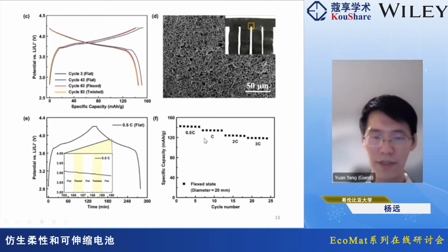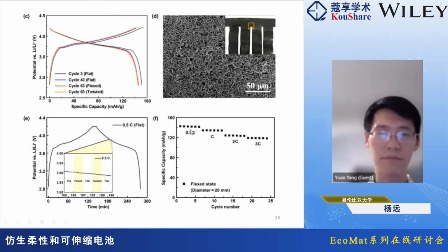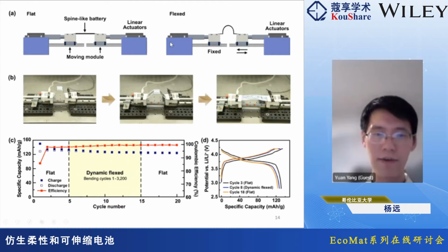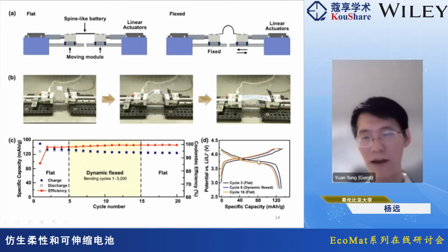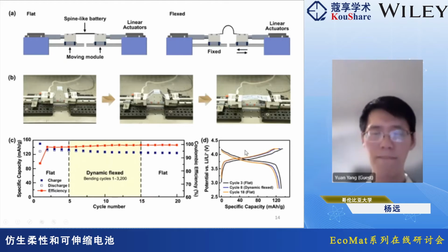And the battery also has a pretty reasonable power output. The rate performance at 3C: the discharge capacity is more than 80% of that at low rate. So we further ran this dynamic cycling test. You can see the different stages: here is bent, and here is the flat state. The capacity is quite steady. During these 10 cycles, we bent the cell 3,000 times, and the voltage profile is also quite stable.